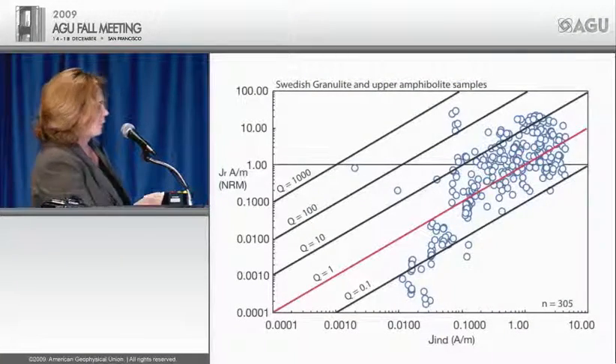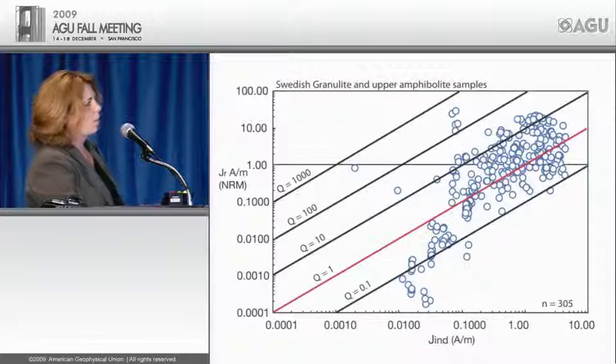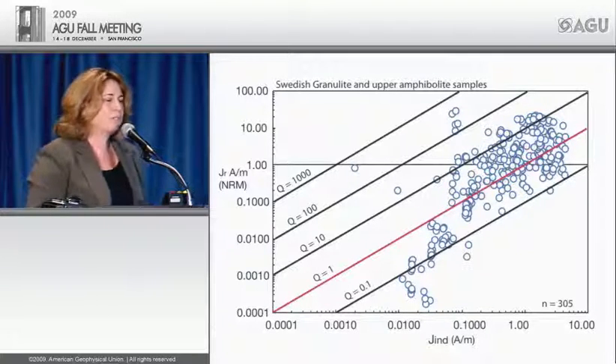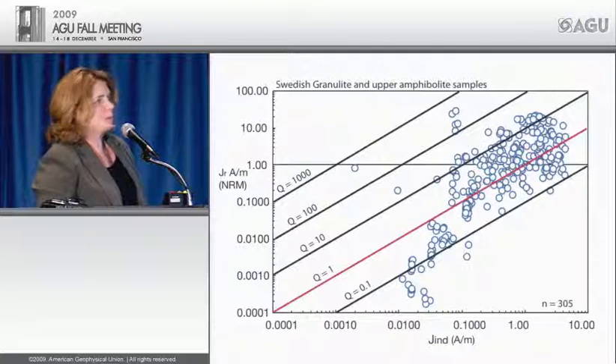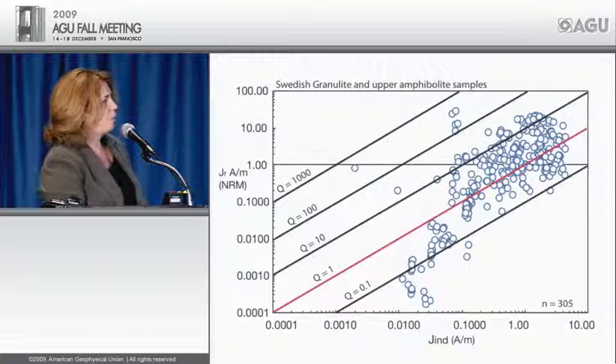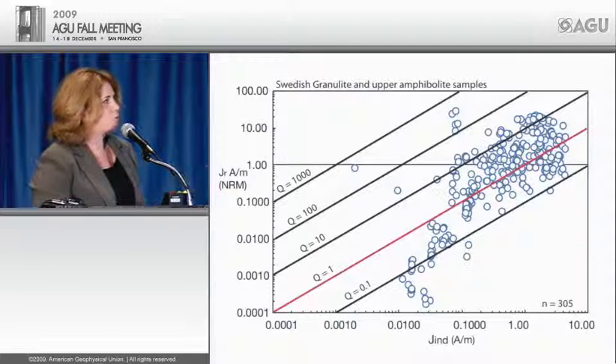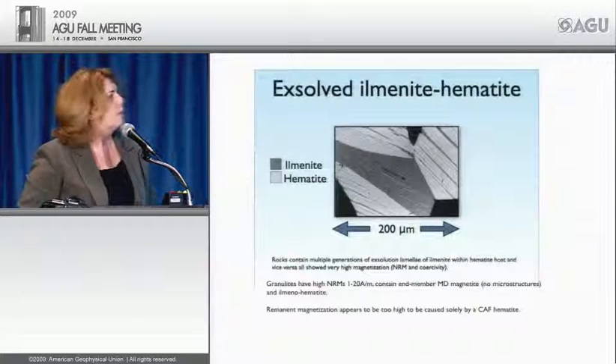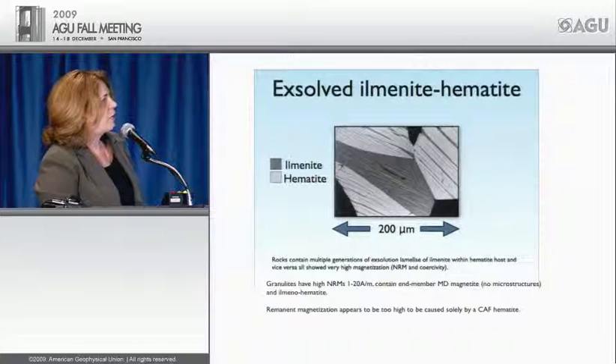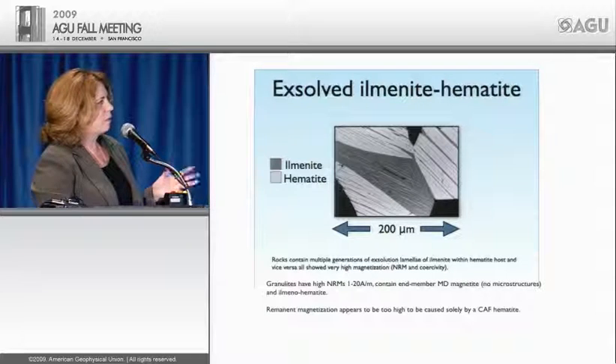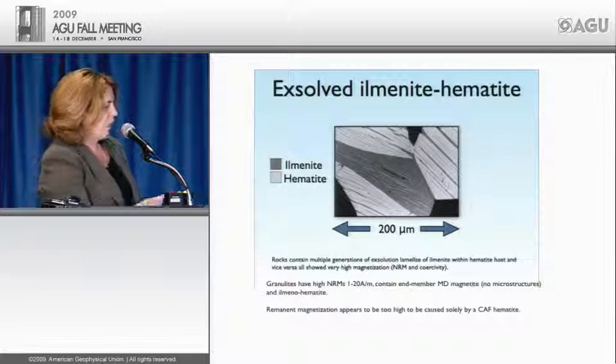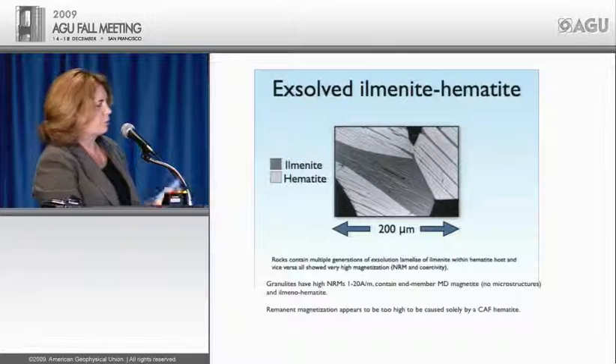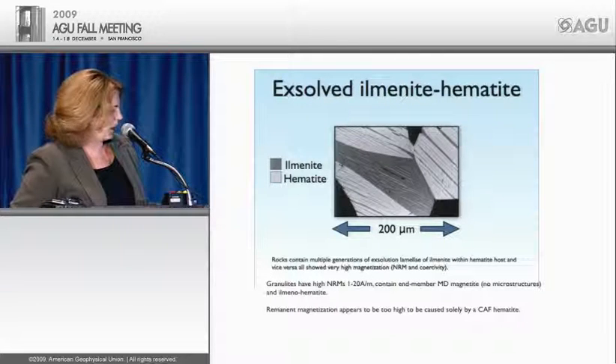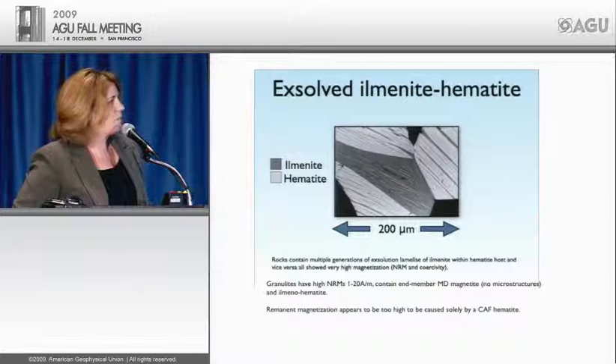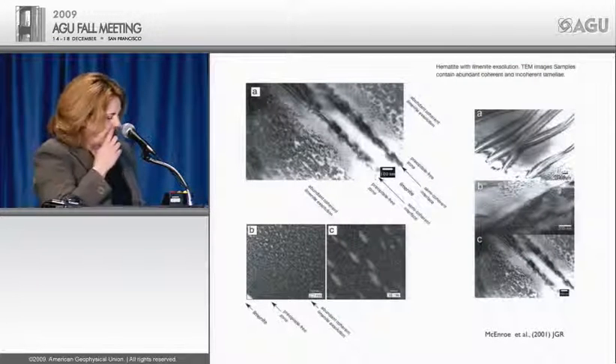And we're looking here at the Q values from a number of these rocks. And one thing I want to point out is many of these rocks also contain multi-domain magnetite. And that multi-domain magnetite is going to carry a large JI component, a large inducing component. So the remanence has to be much stronger than that to end up being negative. So what does this mineralogy look like? I'll mainly be talking about exsolved hemo-ilmenite, and it's an ilmenite or a hematite, which has exsolved the other phase. Often the grains are quite large, and then they have exsolution that continues down to the very fine scale. And many of these rocks have quite significant remnant magnetizations.